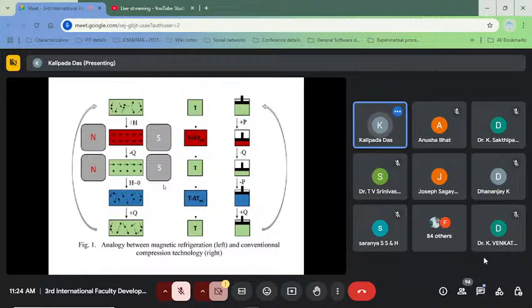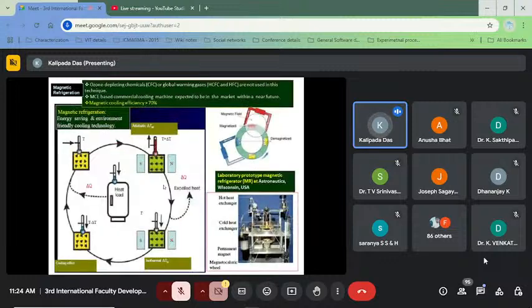The physics behind this is schematically given here. In the case of gas compression cooling technology, a similar phenomenon can appear with the use of magnetic material. That means we can easily transfer heat from the heat load to the environment, similar to gas compression cooling technology. This is the magnetocaloric refrigeration prototype. In this cycle, we have shown schematically that suppose the temperature of the material is T. Now it is adiabatically placed in the magnet. Then its temperature is enhanced to T plus delta T due to the change of the magnetic orientation. That means the magnetic entropy is lowered.